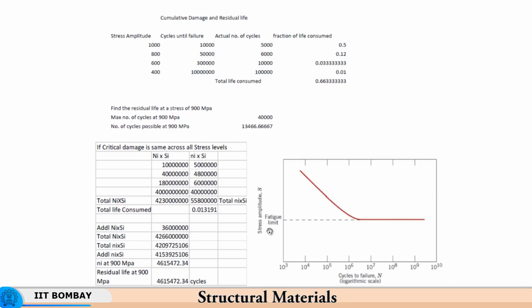So, this will happen when the amplitude of stress is very low, and then the crack or the defect inside does not propagate. So, the stress is too low to get the defect to propagate, in which case we can always get an infinite number of cycles as the predicted life. And so, normally what people have standardized is 10 to the power 7 cycles as the estimate for determining the endurance strength or fatigue limit.